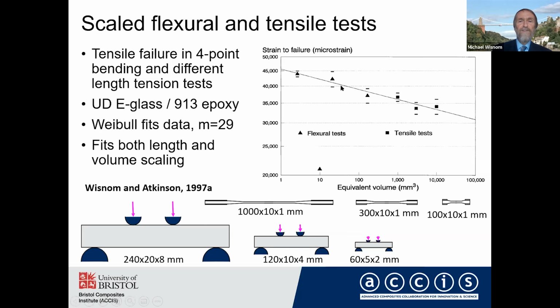And you can see here, we've got the 3 specimens which failed in bending with different sizes, and the reduction in failure strain as you increase the specimen size is captured there. Here we've got the 3 different length specimens, which also fall on this line, and then the fact that the bending specimens show higher strain to failure than the tensile tests is because in the bending test, you've only got a small volume of material which is subject to that maximum stress. Then they all seem to fit on that Weibull line.